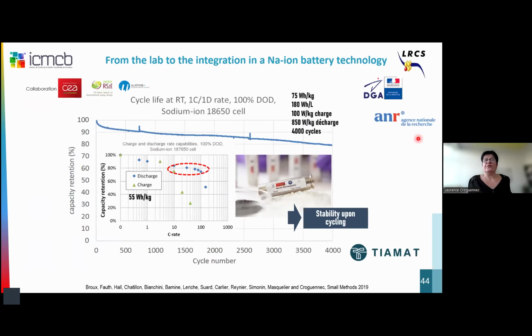So first prototypes were performed by CEA in order to demonstrate the interest of the technology. And you can see that it is interesting here for a power prototype. You can see in blue that we can really discharge the battery at very high rates, and charge the battery in 6 minutes. And we also demonstrated at that time a very long cycling for these materials, so stability upon cycling.